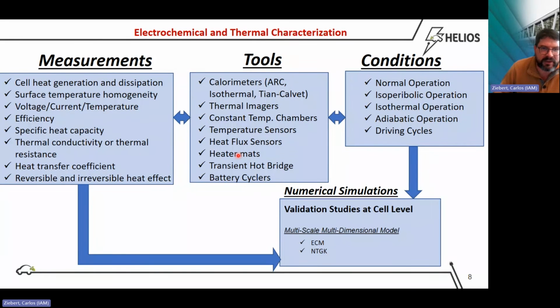So for the electrochemical and thermal characterization, we did all these kinds of measurements with the different tools that we have available, like the calorimeters, thermal imagers, heat flux sensors, and we were investigating normal conditions and different other conditions, also adiabatic operations in the accelerated rate calorimeter, which is a kind of worst case scenario, because then the cell cannot transfer heat to the surroundings. So this would mean that the thermal management would not work under such conditions. And all this goes then into the simulations of the thermal model. Similar for the electrochemical, this goes into the equivalent circuit model.